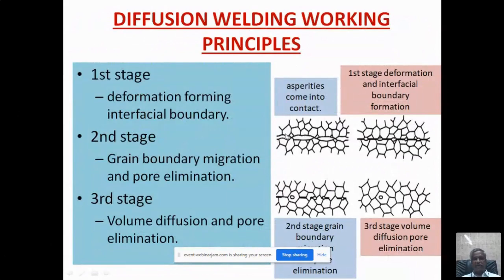Any surface, whatever the polishing method you use, there will be some asperities. Asperities means ups and downs, peaks and valleys on the surface. Roughness will be there. It is very difficult to produce a surface finish to the tune of optical class. So all the surfaces have some ups and downs, peaks and valleys. In this initial stage, there is a contact between the peaks, and there is no contact between the valleys, so there is a vacant site here. But at the peak points, there is contact. So this is the first stage.